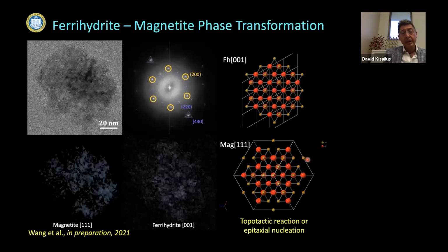Well, we've taken one of the teeth, I believe it was tooth 4 at the top, or tooth 5, and re-examined another particle. And what we found was that same secondary particle that was originally ferrihydrite, a mesocrystalline structure, is now a mesocrystalline structure that consists of both magnetite and ferrihydrite domains. And so what we surmised is that there is a topotactic transformation between, for example, the 001 ferrihydrite plane and the magnetite 111 plane. Again, this is something that we're still examining, but it's pretty exciting.